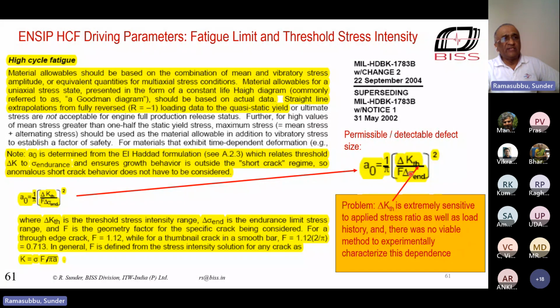And there is a very complicated, convoluted process to determine how fatigue limit varies with mean stress or with applied stress ratio. But in engineering practice, there is no standard method to characterize threshold stress intensity range as a function of applied stress ratio for initial defects. This is very important because initial defects don't see the same conditions as cracks which are grown in experiments to find out threshold. In lab experiments with long cracks, you get a very different threshold.